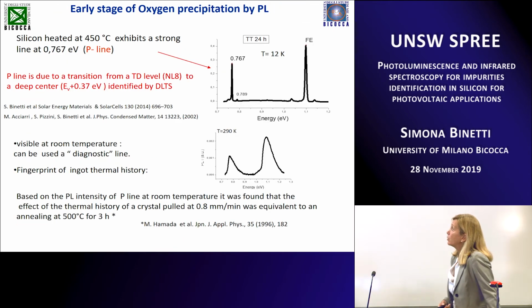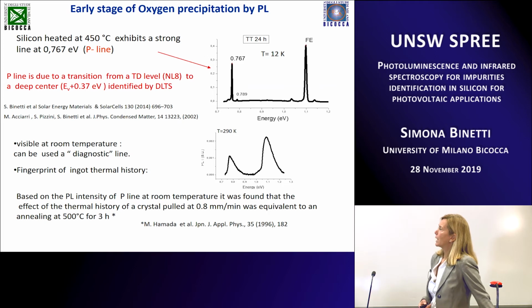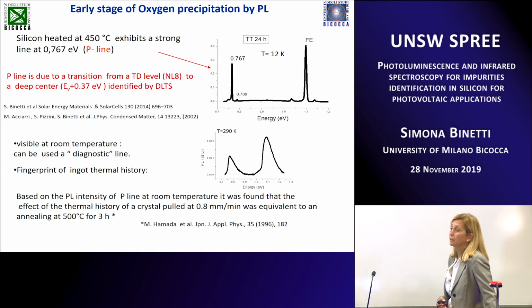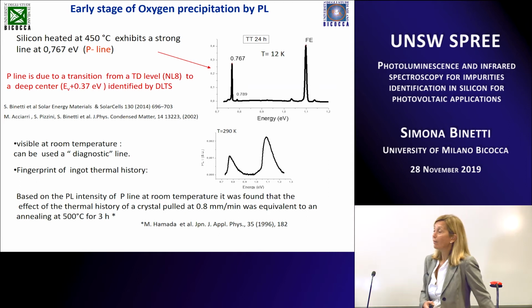By photoluminescence, you can detect at a low temperature, but also sometimes at higher temperature, a band that is called the P band, that is close to the band of dislocation. We will see it at 0.767 eV. Among the thermal donors, we have a big family of thermal donors, but one of these, called NL8, is related to a deep center that has been identified by DLTS. So if you have this line, it means that you have a deep center that can affect the lifetime of your material. And so this is the P line.